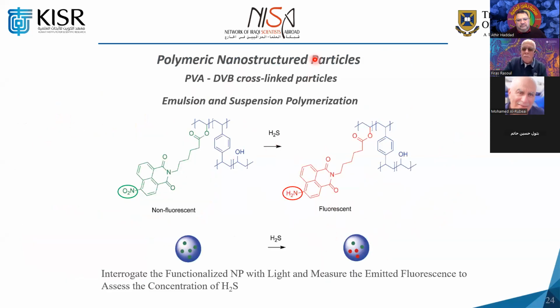This is actually the polymeric nanostructured particles. Mainly, we started with polyvinyl alcohol and divinylbenzene type monomers, and we copolymerized them. This is just to produce a nanostructure using emulsion and suspension polymerization technology. And then we functionalize it with this. And then, of course, this one has a nitro group. It can be reduced with H2S in order to convert it to this. This is non-fluorescent, while this one is fluorescent. So if you inject this material, you will be able to convert it to that.